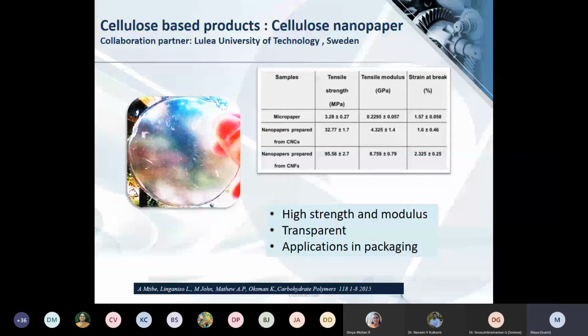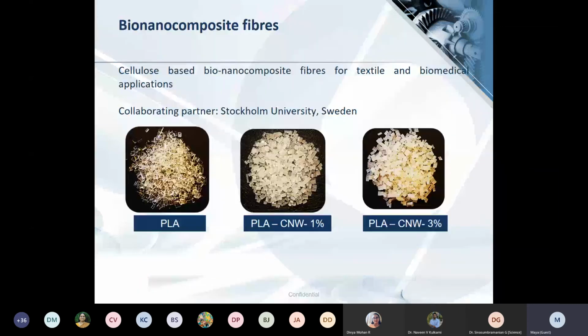And you can see that the nanopapers prepared from cellulose nanofibers exhibit higher strength than those from CNCs, mainly because of the interfibrillar network in these materials and also the hydrogen bonding present. And these have high strength and modulus, and they can be used for packaging applications. So this is also another example of a product that can be derived from cellulose nanomaterials. And here, our collaborating partner is Stockholm University in Sweden.